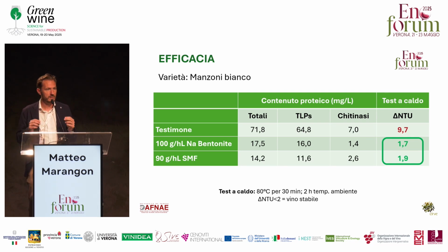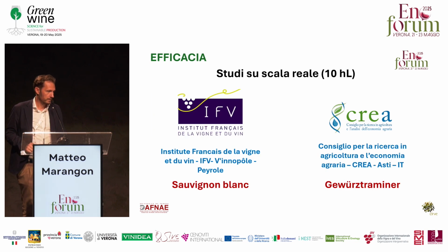So you see that basically the quantity of bentonite is very similar to the quantity of SMF, with a difference of 10 to 15% more or less. In some cases, bentonite works a bit better or vice versa. So we have a similar amount of product to be used, and this is something that is very encouraging, we believe.